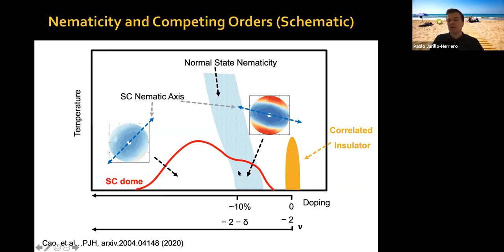In the region of the superconducting dome where there is normal state nematicity above it, and if you suppress superconductivity, there is normal state nematicity there, okay? So it seems that in this region of the superconducting dome, you develop nematicity. These ellipses are pinned by something, probably a little bit of strain or disorder, but of course this nematicity doesn't originate in the strain because it's rotated. Okay, and strain is fixed. We don't change the strain in our sample with doping.